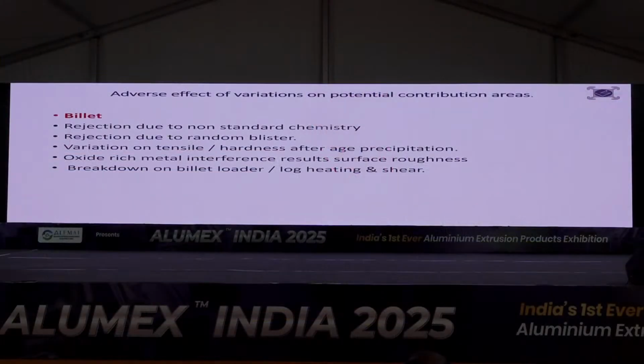Adverse effects of variation, potential contribution areas: rejection due to non-standard chemistry. Sometimes the chemistry goes out, they say just run it. Rejection due to random blister, we have already discussed. Variation in tensile hardness after age precipitation is another area of concern. Most of the places we have a double rack aging system in batches. So the entire aging oven has to have an equally balanced thermal management system so that the entire furnace has the same temperature, more or less.